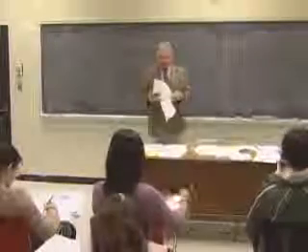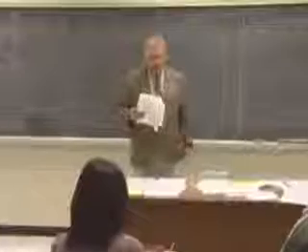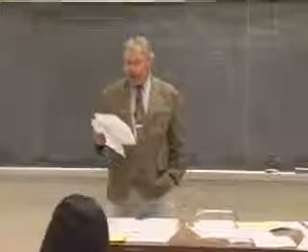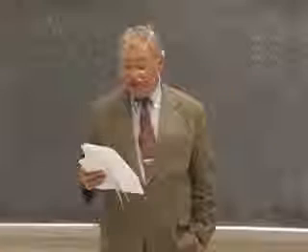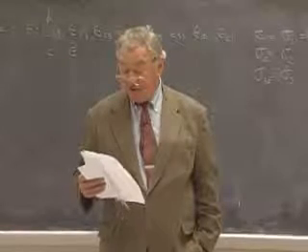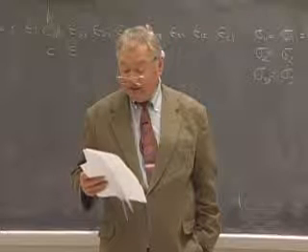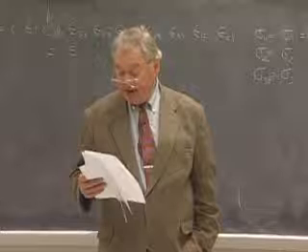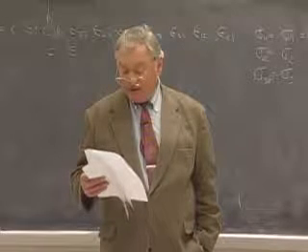Some additional bits of information. The transformations for hexagonal crystals are complicated because threefold and sixfold axes do not change the reference axes x1, x2, x3 into one another. And the equations that relate the individual tensor elements are more complex.